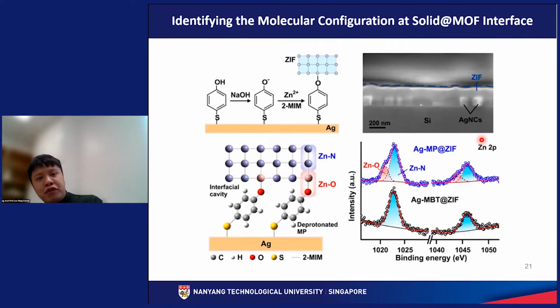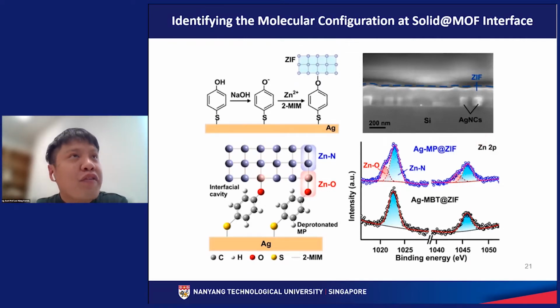So first up, let me briefly go through what is happening in our reaction system, or how to form our reaction system. So initially, we graft mercaptophenol onto our silver nanocube surface. Again, this uses silver nanocube. We try to treat it with sodium hydroxide to form the phenoxide moiety. After which, we add in zinc precursor as well as 2-methylimidazole precursor to form the MOF layer. Okay. This is again the cross-sectional view of our platform, whereby this is silicon, silver nanocubes are over here encapsulated in the ZIF thin film.